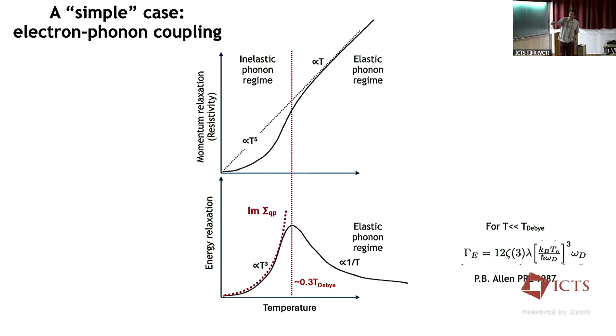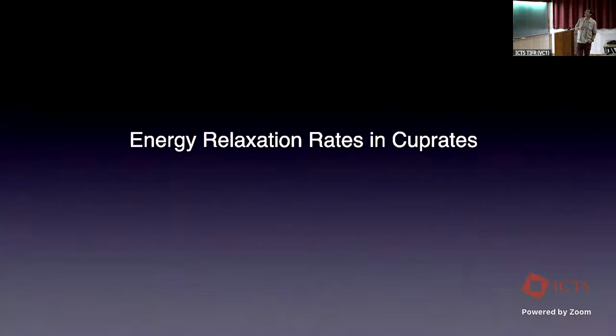Oh, and then this T to the 3rd, at the lowest temperatures, is very, very close to the contribution of the electronic self-energy from the electron-phonon interaction here. So at low energies, at low temperatures, you expect that this energy relaxation rate tracks the contribution of the quasiparticle self-energy from phonons.